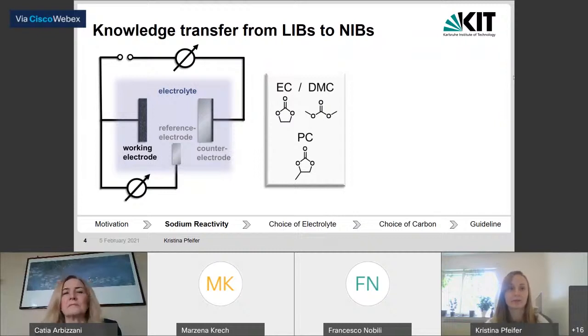We know that lithium is very stable in the commonly applied carbonate-based electrolytes, which are shown here, like these different carbonates with the respective alkali metal salt. But in the literature, the enhanced reactivity of sodium was mainly neglected, and the electrolytes were just taken over from LIBs with the respective sodium salt and sodium metal as counter and reference electrode.